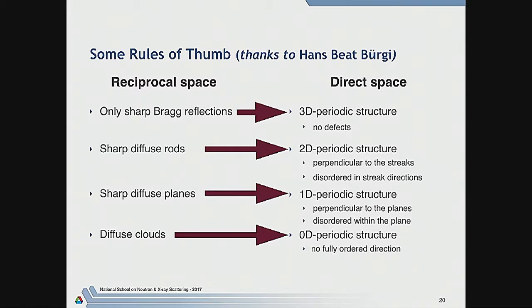If you see rods, that tends to mean that there's some kind of two-dimensional disorder perpendicular to those rods, which is uncorrelated. So if you have stacking faults in the material, which are uncorrelated with each other, then that will produce rods, very similar to the truncation rods that some of you may be familiar with from surface X-ray scattering, for example. But of course, you can also have three-dimensional disorder.